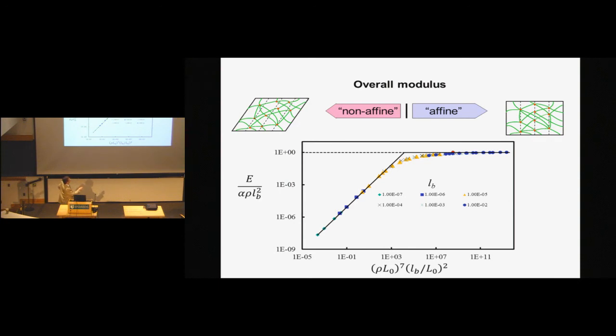This physics I described simply tells us that if the network is really dense, that is rho is large, or the fibers are really stiff in bending, that is LB is large, when I'm moving to the right in this plot, my network behaves as a homogeneous body. While when the density is small or the fibers are really floppy in bending, my network behaves as a highly heterogeneous body. Okay?